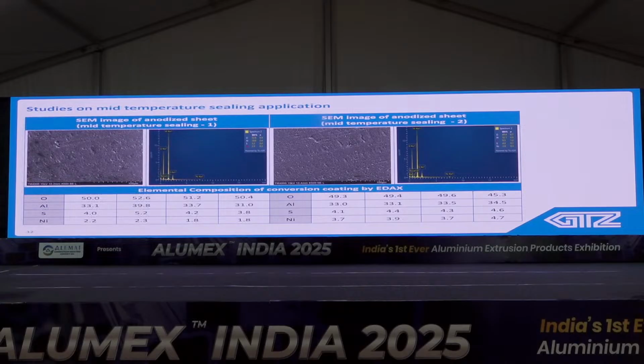Now mid temperature sealing. Here the left side is the SEM and EDX picture of the half sealing, meaning if 10 minutes is required for complete sealing, it is after 5 minutes. Here only nickel is found as elemental composition, and on the right-hand side it is the same picture and composition analysis of the full seal. You can find from the nickel content that after full sealing the nickel content has increased. It is around 4.2, and at half sealing it is around 2 to 2.2. That means the nickel hydroxide or nickel is also getting involved in the sealing process as metallic hydroxide.